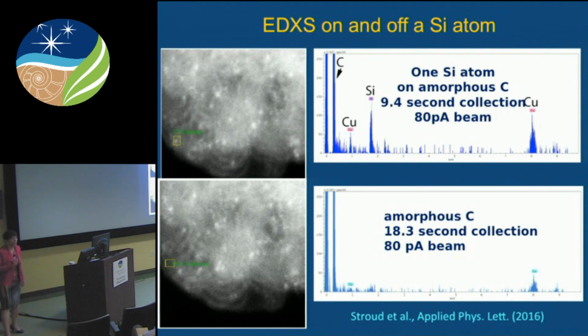We can actually measure impurity by impurity. So we can put the raster box down around a single impurity atom and count X-rays off of that atom and off the underlying carbon, and see that it's silicon. So in 9 seconds with an 80 picoampere beam, I can tell you what an individual atom is.